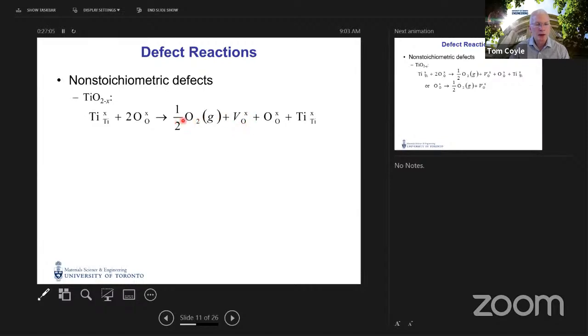The oxygen has gone, but we imagine that it's left its 2 electrons behind, and therefore the relative charge is 0. We need to balance mass and site, so the second oxygen ion remains in the lattice on an oxygen site, and the titanium cation remains in the lattice on its titanium site. So that's a possible defect creation reaction describing the loss of oxygen to the surrounding atmosphere. That may not be all that happens.